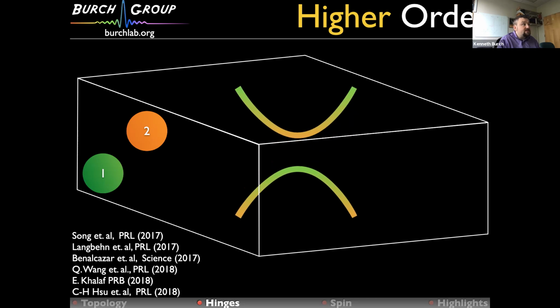What you'll notice has happened is electrons have physically shifted from sitting mostly around atom 2 to now partially sitting around atom 1. It's almost like I've made a ferroelectric. Of course, I haven't, because I have inversion symmetry. But nonetheless, the states sitting in this valence band are no longer mappable back to the atomic limit, because they've now physically moved. It's like I've shifted the charge. And it turns out that in such a scenario, if you were to calculate some topological invariant, you could find that indeed you had this non-trivial topology. Your Berry connection had gone through a divergence, if you will.